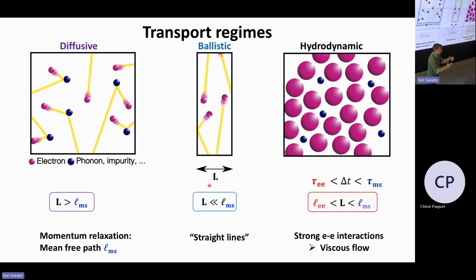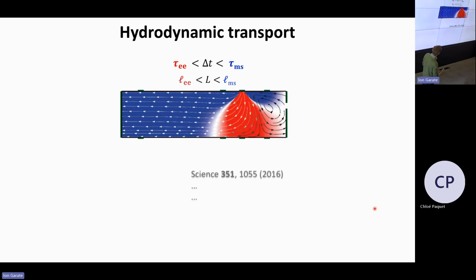So they're interacting more with electrons than with impurities. And you can imagine that if you want to have transport of such a system, it's more like a viscous liquid. This is also why it's called a hydrodynamic regime. So it's more like a water type flow through a pipe. And this is the regime that you get when you have a length scale of your system or your time resolution equivalently, that is in between the interaction length or time of the electrons and the interaction time or length where you have interaction with phonons. So around time zero in our experiment, we're in this hydrodynamic regime where you have this viscous flow.